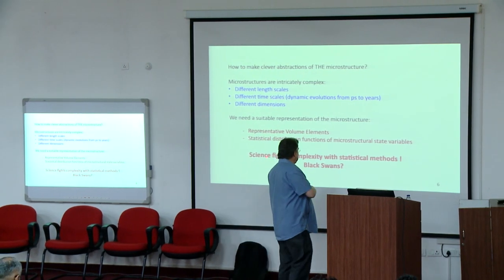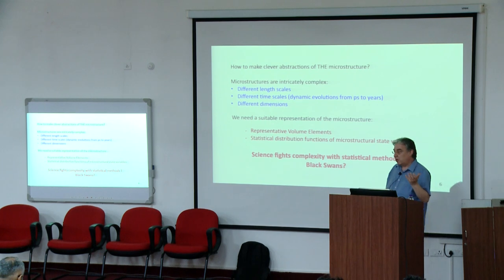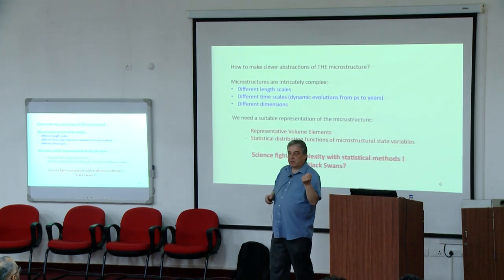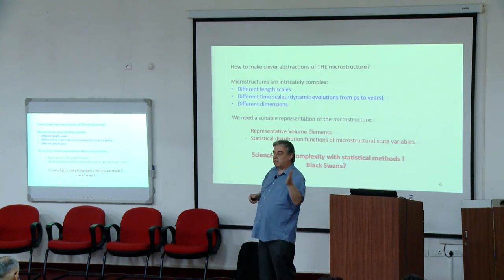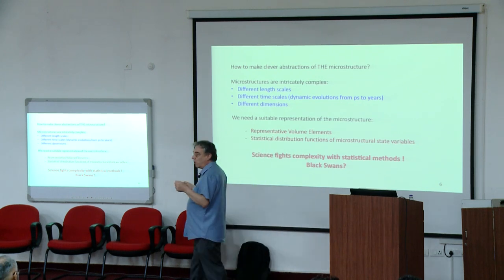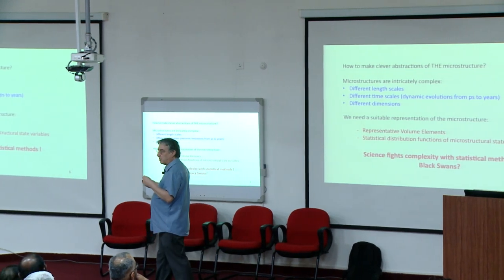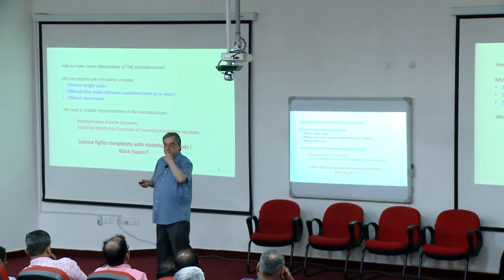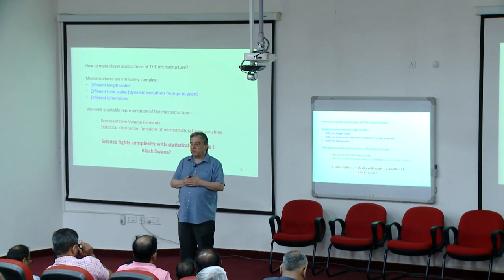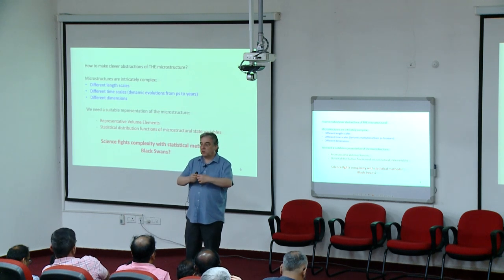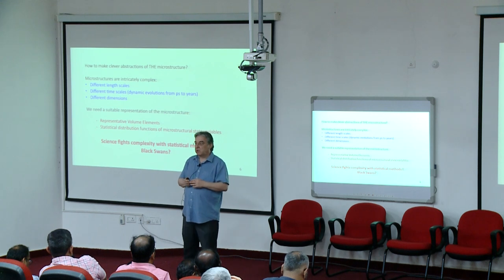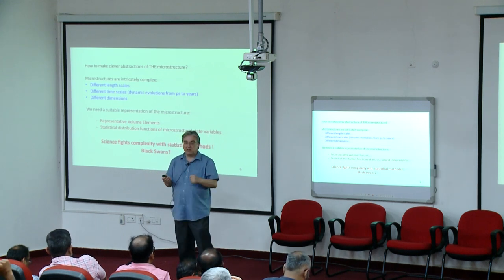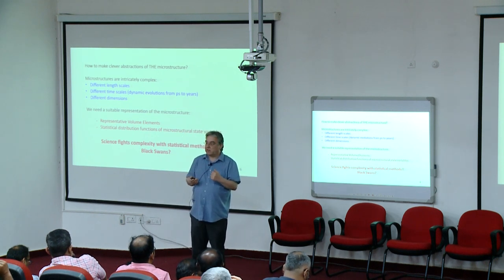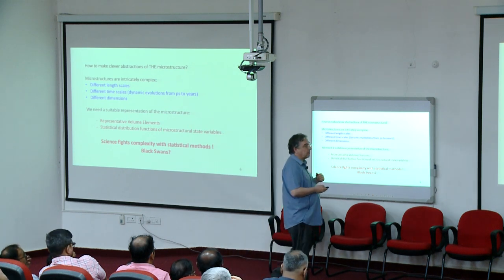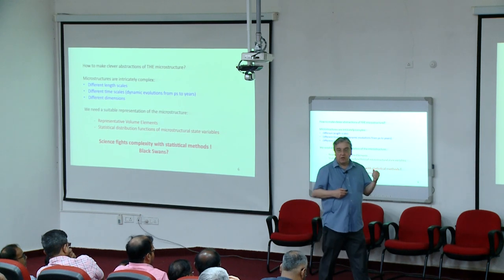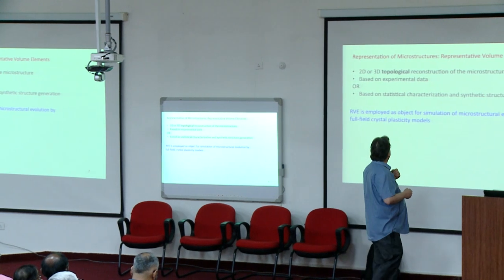Of course, will this tell you the whole story? No. Because you've probably heard of black swans. These are elements that are totally outside of the normal distribution of things, but that may play a role. We have to be aware that they exist. You find this, for those who are familiar, in a phenomenon like secondary recrystallization, for example, where you have one single grain, and this grain will grow and consume the entire matrix. It may even grow into a single crystal. That single grain is kind of a black swan. That will be difficult to describe by statistical methods. So like all methods, statistical methods also have their limitations. But for the time being, let's assume that, with statistical methods, we can see how far we can go.